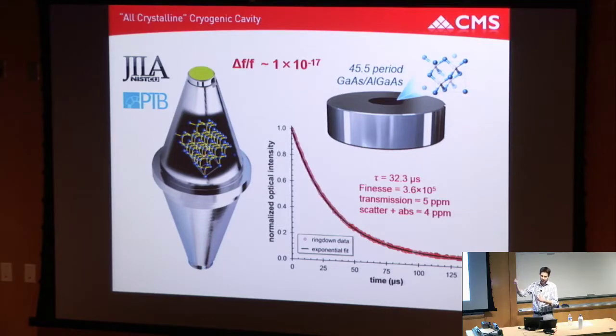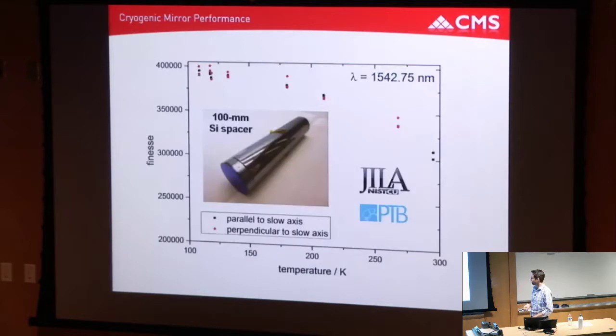So you're starting to measure the coherence length of these laser systems in terms of astronomical units. But this is what it takes to make better and better clocks. So we built a test cavity on a single crystal silicon spacer that was 10 centimeters in length and then measured the finesse. One tough thing is that because of the thermal refractive effect, we have to redshift and design the mirrors for a longer wavelength than intended at cryogenic temperatures, because as they cool, the center wavelength shifts.